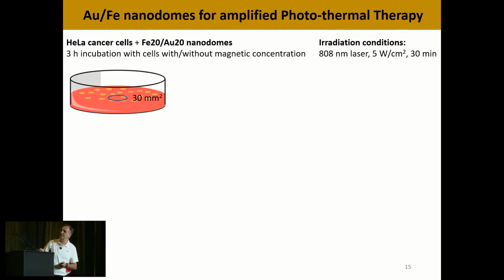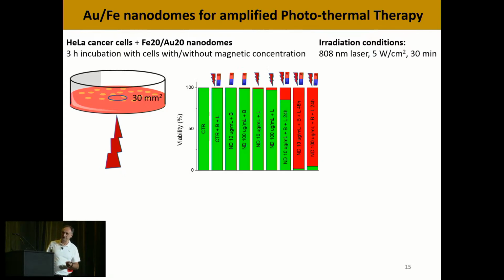We had some HeLa cells in a cell culture, and we put nanodomes with 20 nm iron, 20 nm gold. Then we tried with a magnetic field, with light, without magnetic field, and different combinations. When we have light and magnetic field without particles, nothing happens. All the cells survive 100%. When we put nanodomes with magnetic field only, nothing happens. When we put light with a small amount of particles, 10 micrograms, there is already a small decrease in cell viability. When we increase the concentration to 100 micrograms per milliliter, with the laser on, there is a little bit more cell death.